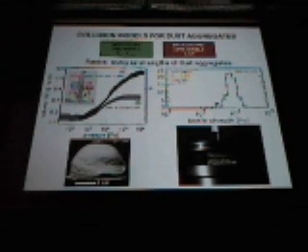The second model is the macroscopic model, the SPH, smoothed particle hydrodynamics model, where numerical particles are treated and the input parameters are macroscopic material properties: the compressive strength, the shear strength, and the tensile strength. Again, the compressive strength can be derived from this 1D curve I already showed you, the Blum and Schräpler curve, or in the meantime we already did that in 3D, which is this one, which yields roughly the random close packing.